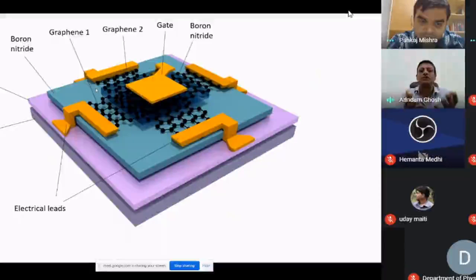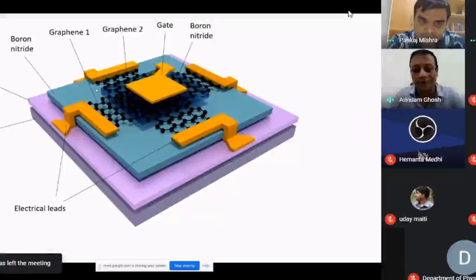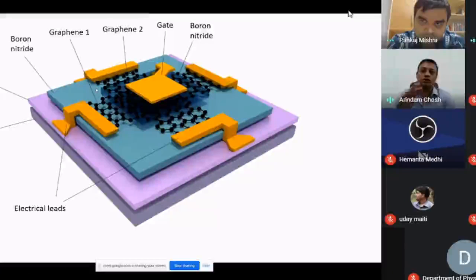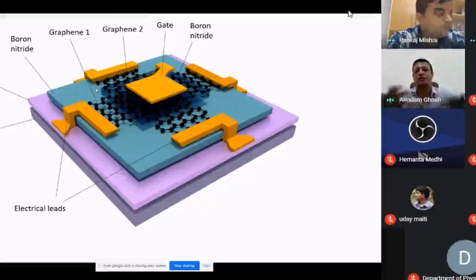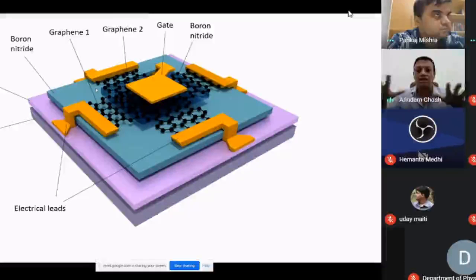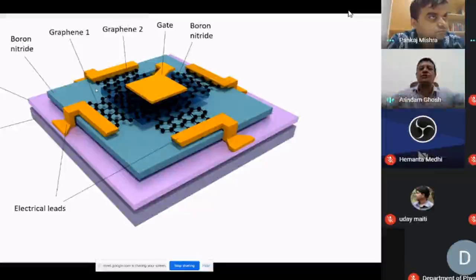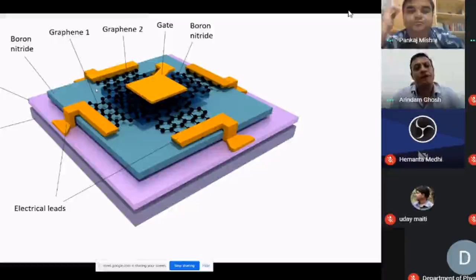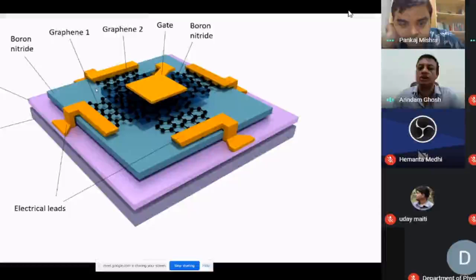What you do is take tungsten disulfide or tungsten diselenide, which are TMDCs, strongly spin-orbit coupled materials. They're semiconductors, but you put those below graphene because they don't contribute to electrical charge transport. They essentially induce some spin-orbit interaction in the graphene layers. And with that, people have found some topological insulator behavior, some non-locality in the current flow, and spin effects. So those are the directions people are thinking at this point.